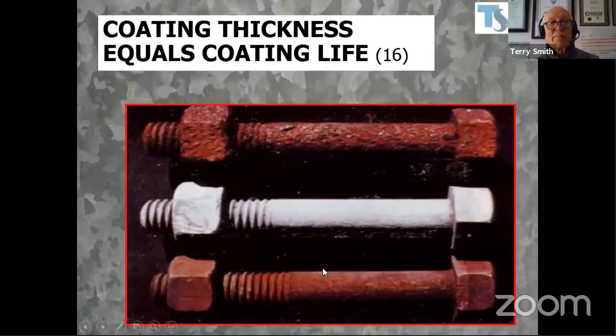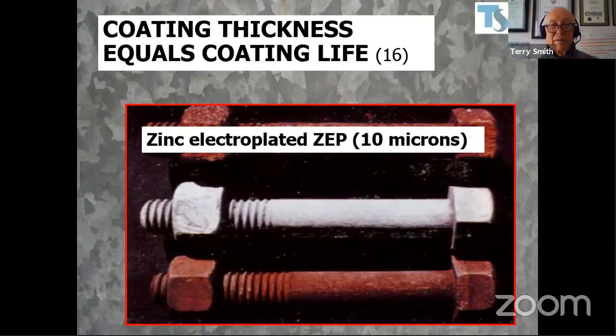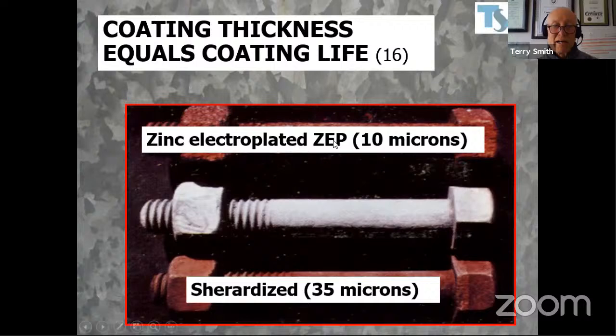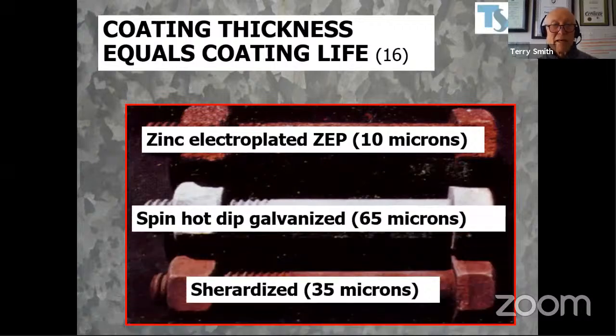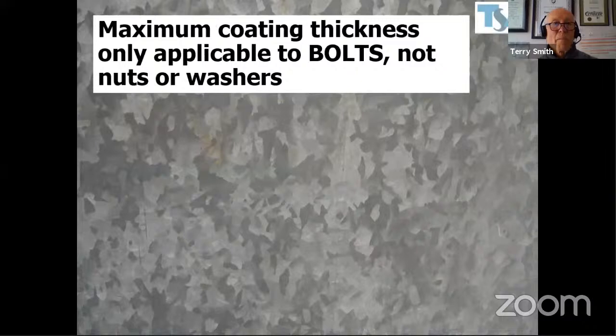Here you can see 3 bolts subjected to an accelerated weathering test: zinc electroplated at about 10 microns, Sheradized at about 35 microns, and spin hot dip galvanized at 65 microns. And purely by coating thickness, the galvanized one has outperformed the others.